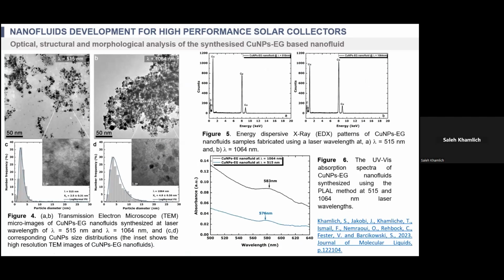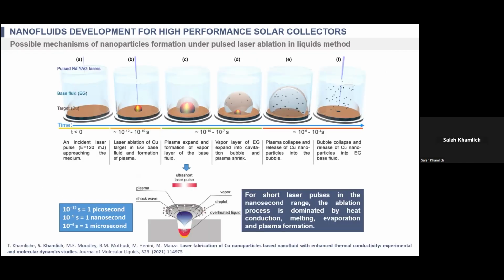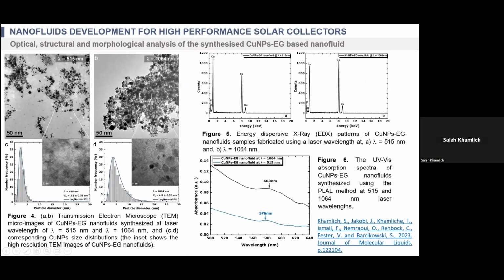So these are some results coming from the nanofluids that I showed you here. This is morphology, of course. These are nanoparticles. Here we used a high resolution transmission electron microscope. Of course, we used different lasers. We used a laser operating at 515 nanometer wavelength, and we used another laser, also at the picosecond regime, but with a different wavelength. Here, we wanted to find out the impact of the wavelength on the production of the nanoparticles.